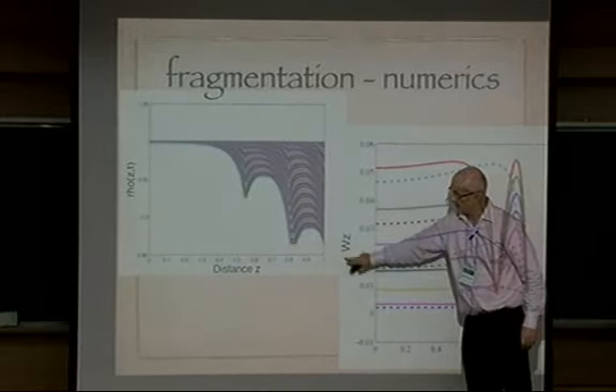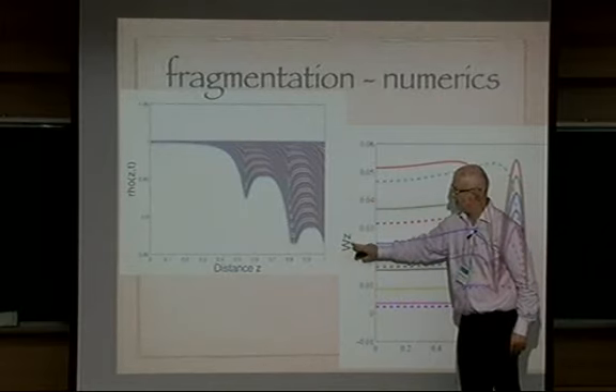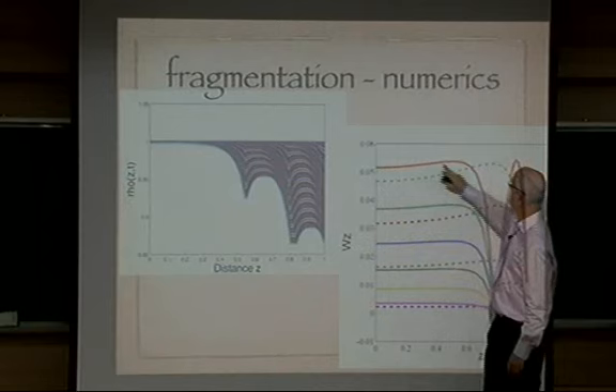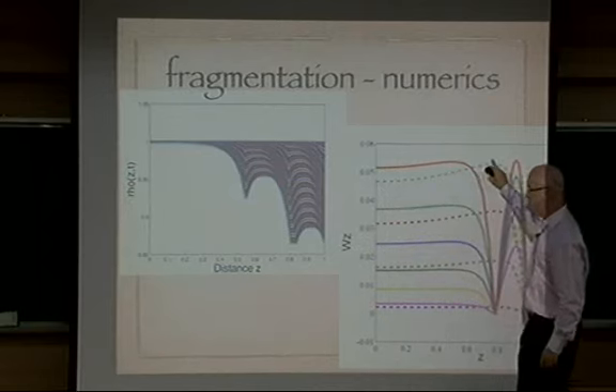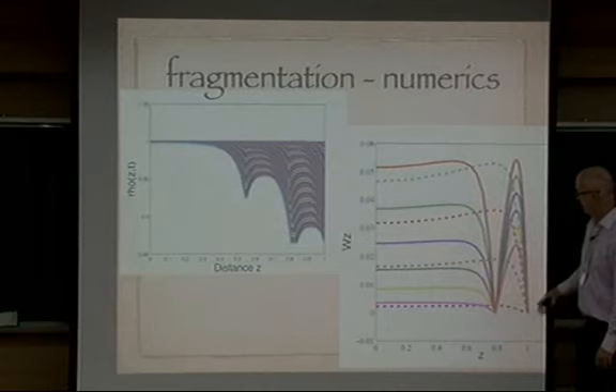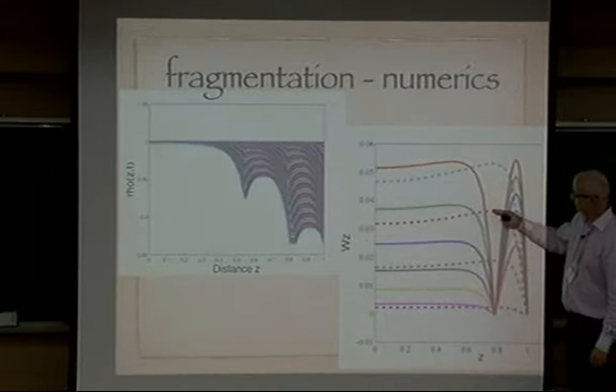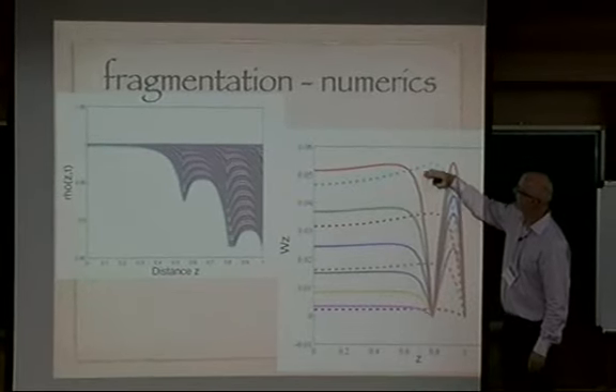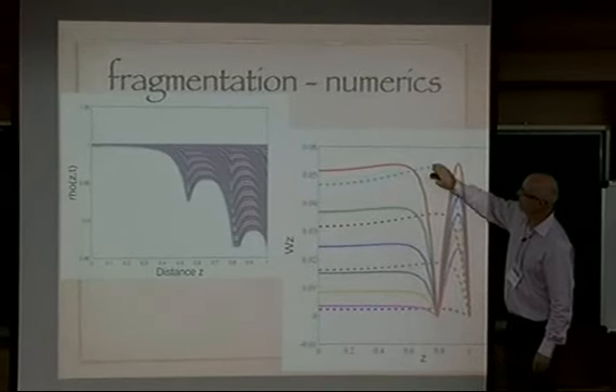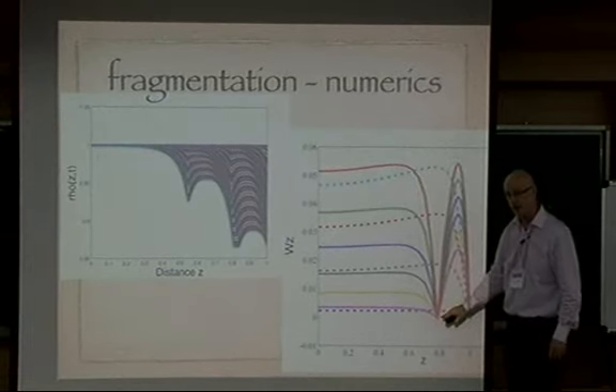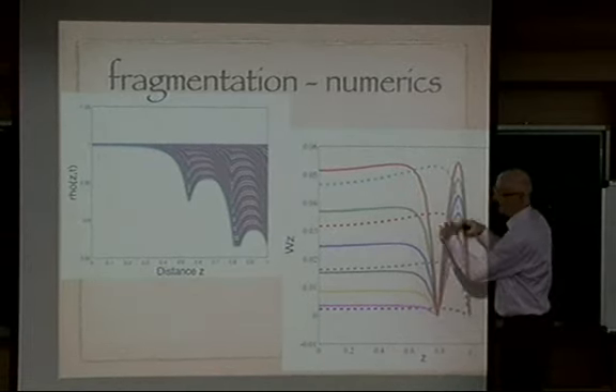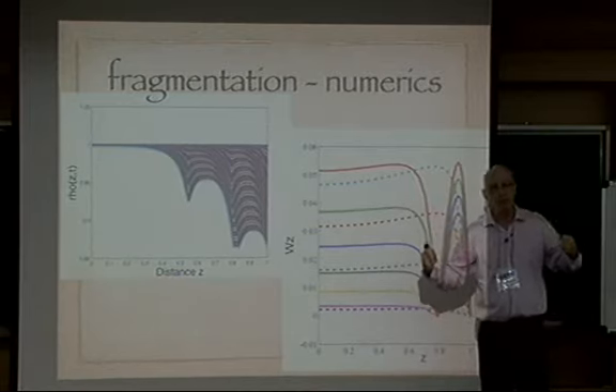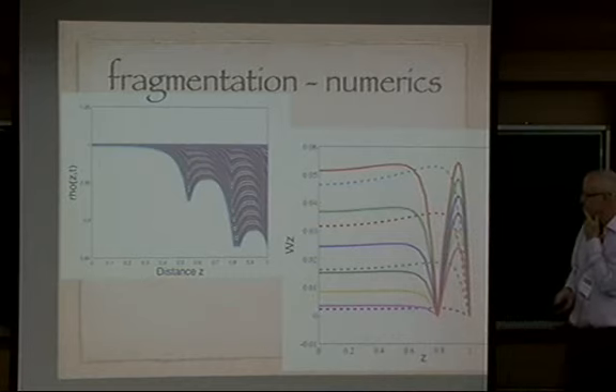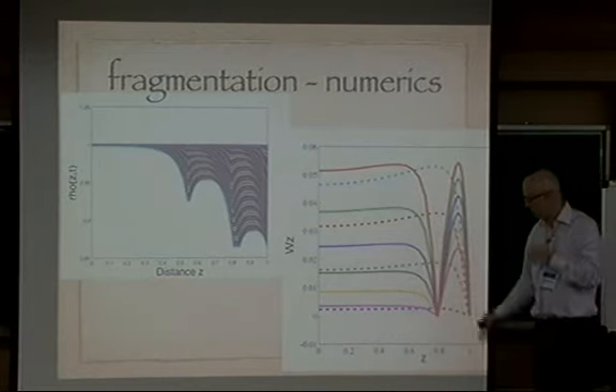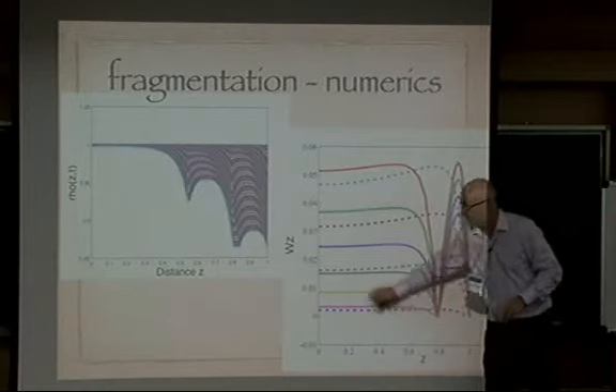Here's that stress, the strain, stress, dWdz. Critical value for dWdz was about just below 0.06 for this particular setup. And we see at early time the stress rising, and there's a slight local maximum there. And then when it reaches the critical value, breaking here, and suddenly I'm dropping stress to 0 there, and then the stresses are rising again. They're rising because the gas is flowing faster and faster and applying more and more stress. So it works, and we get a length scale. There's the first breakage, and then the second breakage and third breakage. The length scale comes from that.